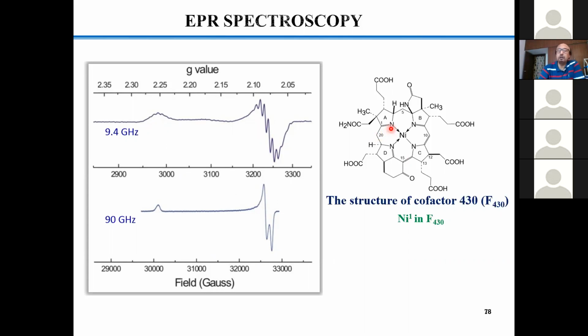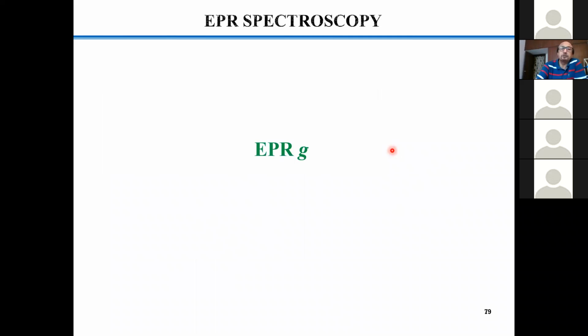But some people thought from X-band EPR that there's some kind of nickel-solvent interaction, they could feel it. But they could not establish that fact because there was no crystal structure. Okay, people could not solve the crystal structure in those days. As a result, they went for the high field EPR, and they could see the rhombic feature. And that tells us that along the g-axis some ligands are there, of course in a weak sense, not in a very strong sense. Okay, so this is how high field EPR is very, very helpful for certain reasons.